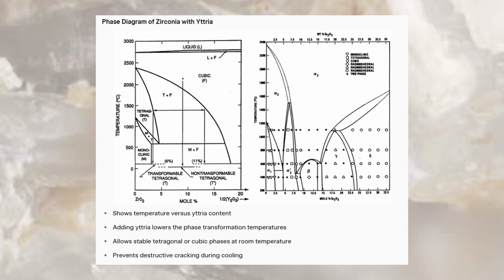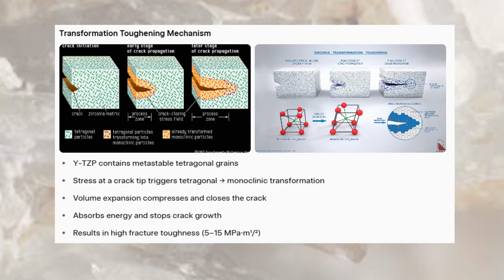So adding yttria, again, lowers the phase transformation temperatures. It allows stable tetragonal or cubic phases at room temperature. This is the transformation toughening mechanism. Y-TZP contains metastable tetragonal grains: a stress at a crack tip triggers tetragonal to monoclinic transformation. Volume expansion compresses and closes the crack. It absorbs the energy and stops crack growth, and this results in high fracture toughness.